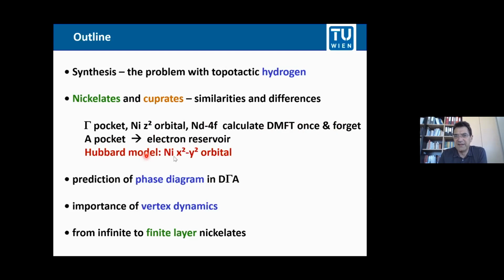So if you describe the nickel x² minus y² orbital with the Hubbard model, you have to carefully translate the doping because part of the doping is going to the A pocket, but the A pocket and the x² minus y² orbital don't talk to each other. They don't hybridize. And because of that, it is more like a passive bystander, a reservoir where you can put holes into.